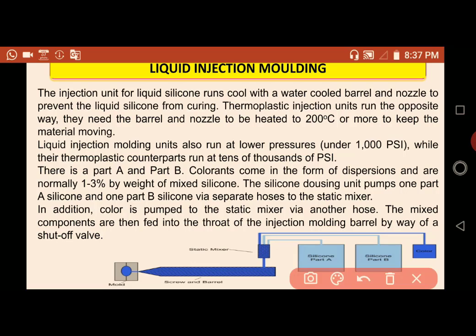Whereas a thermoplastic injection unit runs in the opposite way. That is, they need the barrel to be heated, depending on the type of plastic we are using, from 200 degrees centigrade or more. Then after processing, it is injected, and the product is formed in the mold, where the mold is cooled for thermoplastic. But for liquid injection molding, the material should be heated in the mold. And the liquid injection molding units also run at low pressure, less than 1000 psi, whereas in thermoplastic injection molding, tens of thousands of psi is required.